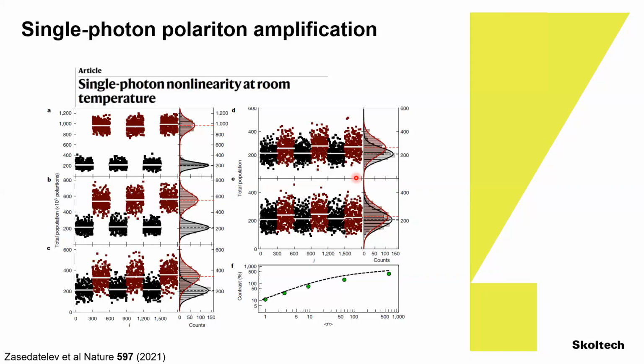So for every pulse of light, we do the full characterization, hundreds of thousands of those, but as we reduce the energy or the number of photons on the control beam, we see that when we are approaching now 1, we still have a 10% contrast between the spontaneous condensation and the amplification. So really just down to the 1 photon, we would discriminate at 10%, not 17 dB, but with 10%, we would discriminate the on from the off state. So when we put together this optical switch, if you like, we were very happy at the time.